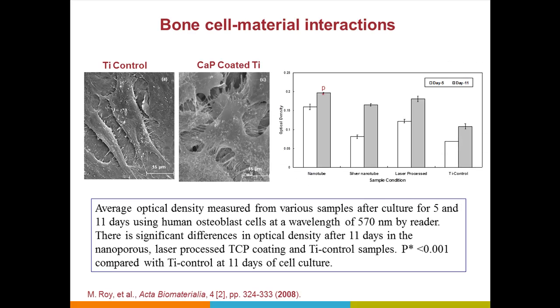To show what happens in terms of basic biocompatibility: this is my titanium control, this is the laser processed, and this is the nanotube or other types of nanotube samples. You can see that by doing the laser processing, between day 5 and day 11, we can enhance bone cell integration on the surface much better than before.